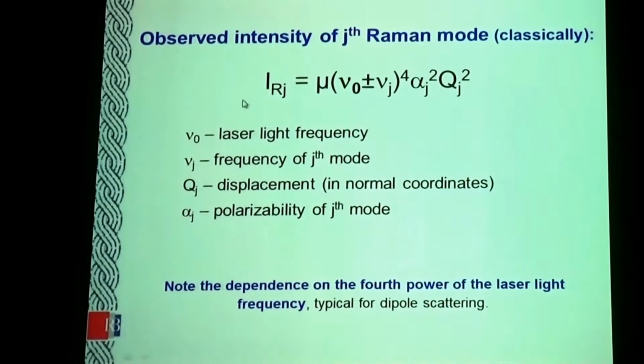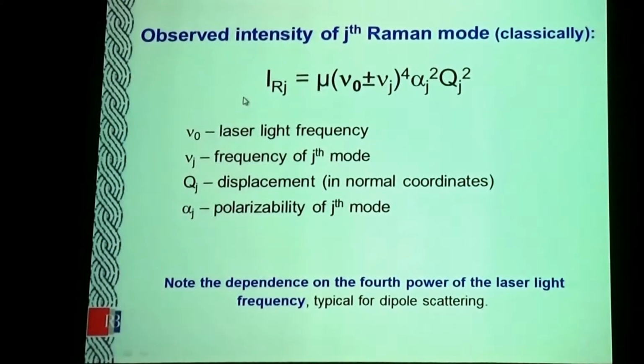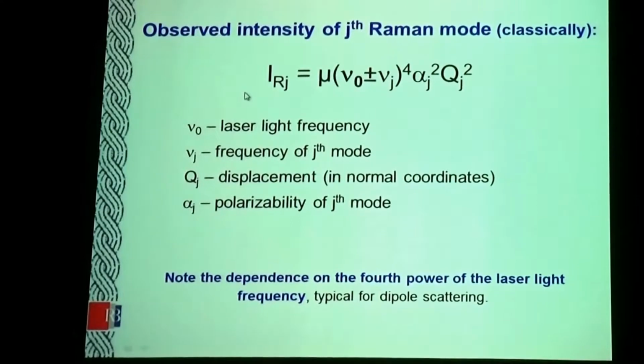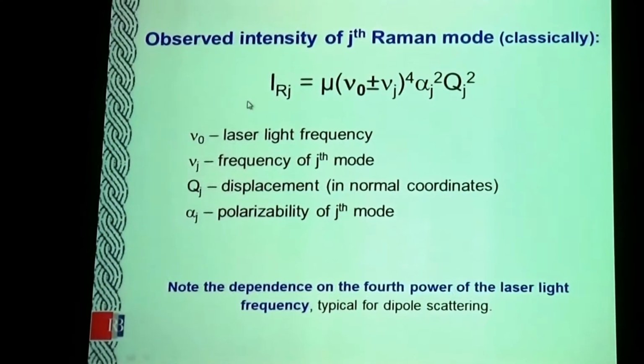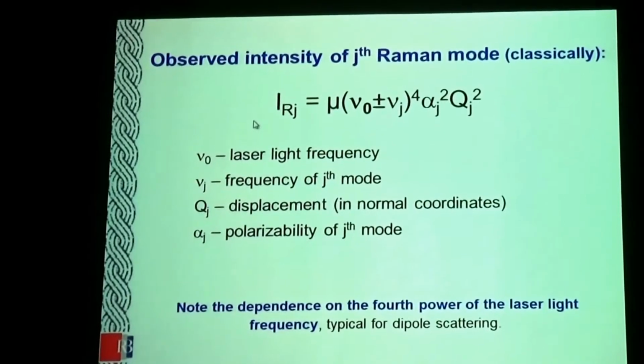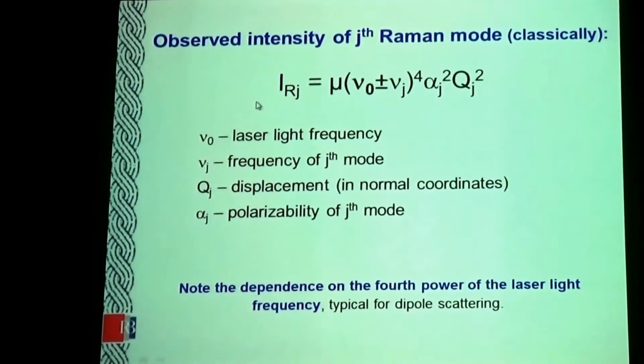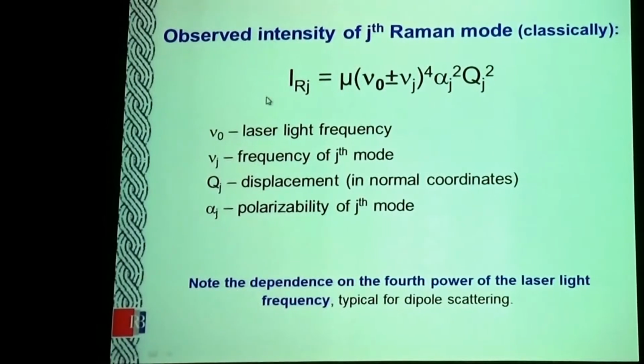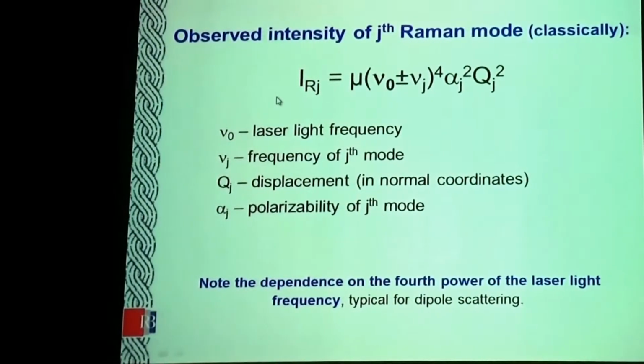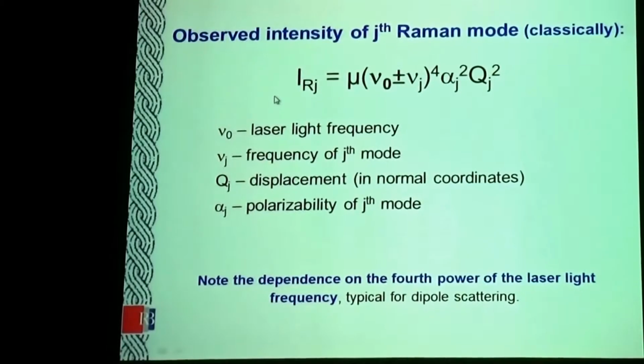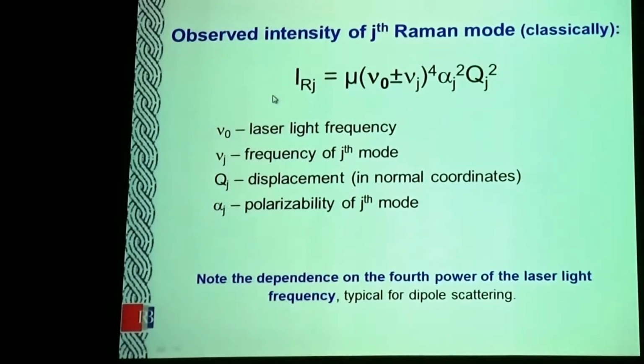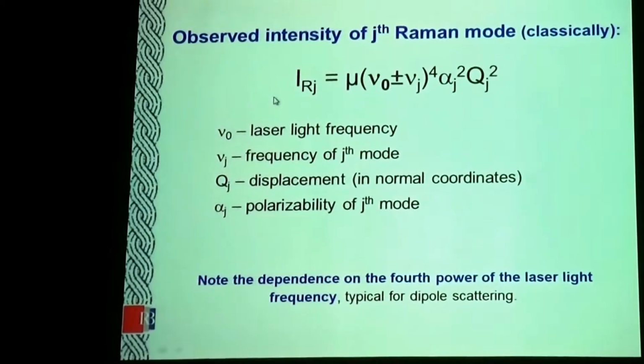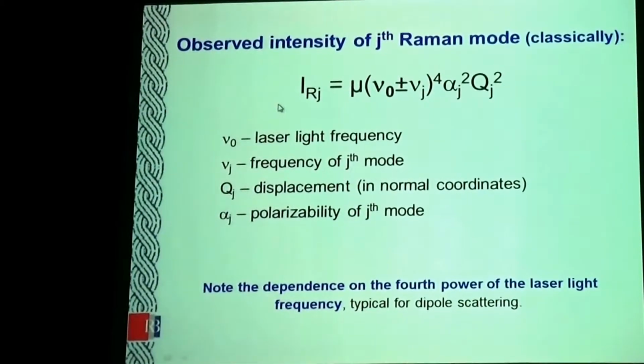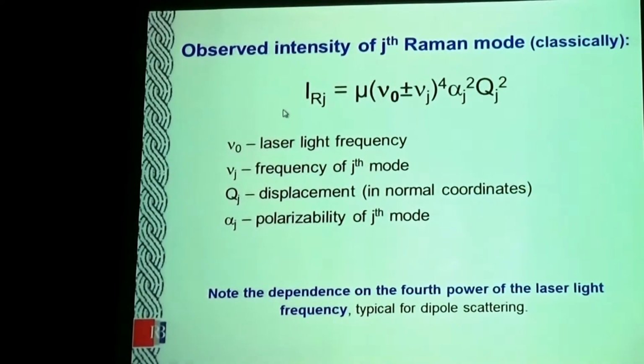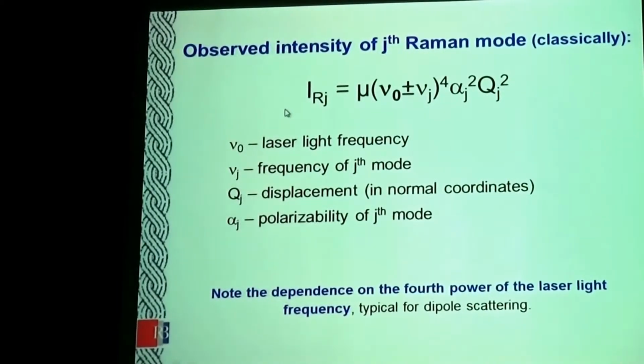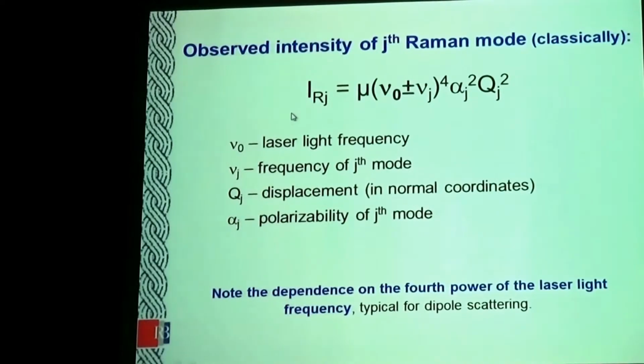However, if you use, for example, a green line, which we usually use, or blue light, then you can have much larger intensity. But sometimes, due to the energy of your laser, in some systems, if you have electron levels which are very nearby, your laser will induce excitation in electron states. So instead of a Raman spectrum, you will have just a large, broad peak of fluorescence due to the electron transition.